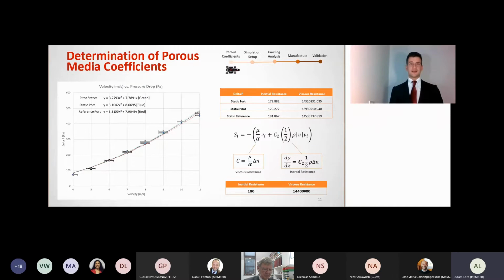The graph in this slide plots the relationship between the inflow speed read by the anemometer and the pressure drop on the corresponding y-axis. Then, by relating the equation of the graphs to the momentum equation for porous media, both coefficients could be obtained. In this case, 3 sets of coefficients were derived, again because there were 3 sets of static pressure ports in place, and an average of these 3 sets of coefficients was used as the final coefficients later on in the computer simulation.